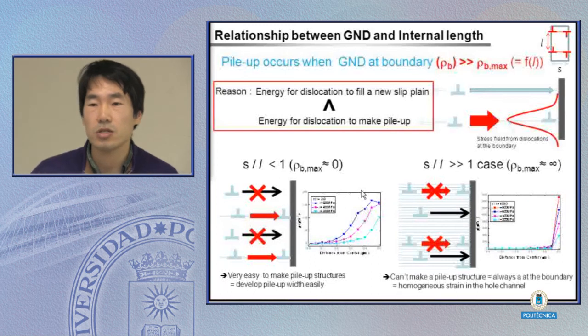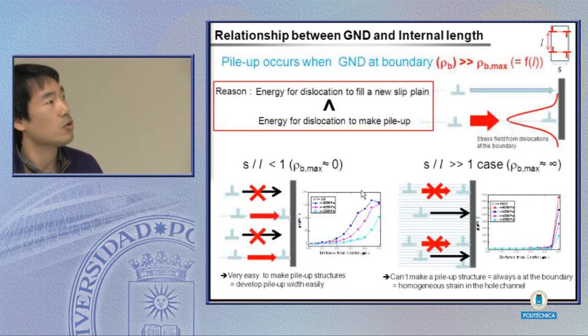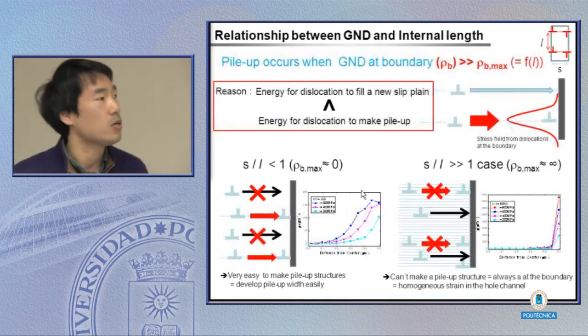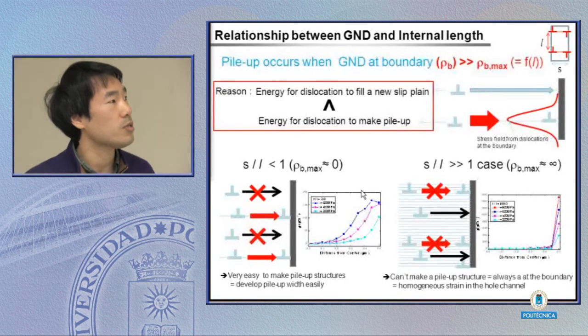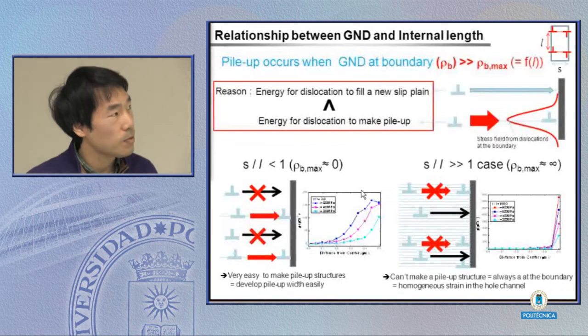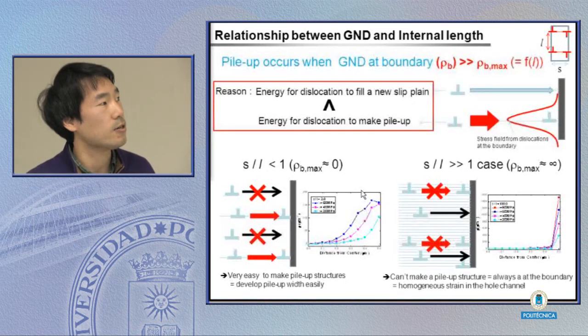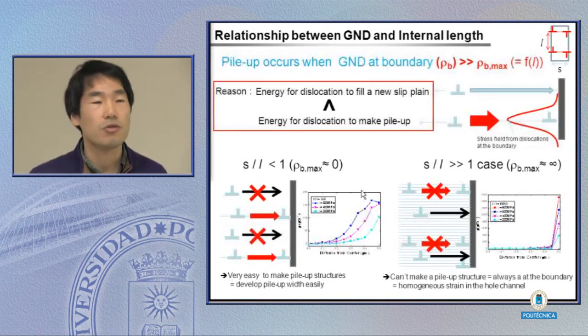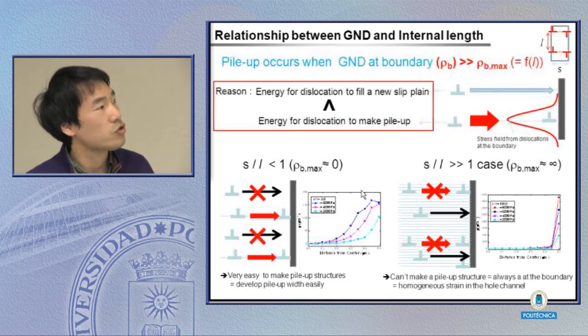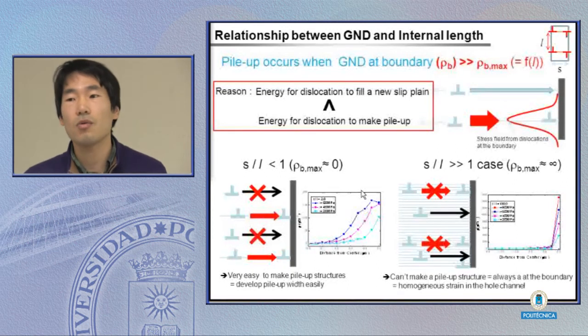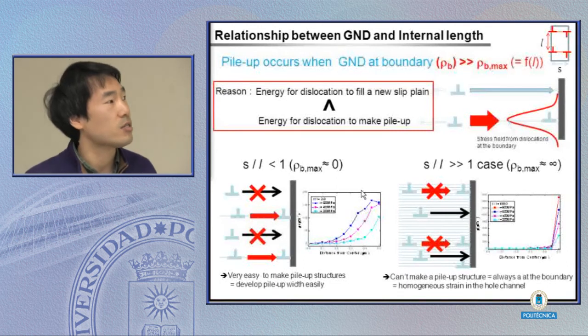You can explain this result using only one assumption. Dislocations pile up only when the slip planes at the boundary are filled with dislocations. The reason is that a dislocation making a pile-up always needs higher energy than a dislocation filling the empty spaces.